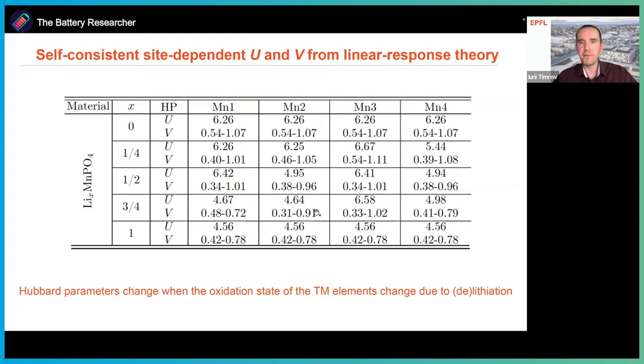So this is quite important to do consistently, because what is done in the literature nowadays is that people use empirical Hubbard parameters, for example, by fitting to the experimental oxidation enthalpies, and they use a unique global value across all concentrations of lithium. That's quite a drastic approximation. Nonetheless, it gives quite good results. Not sure if always, but in some cases it does. But what we do here, we really take into account more accurately what happens at the electronic level. We really computed it site dependent. So how each manganese changes its electronic state, its oxidation state, so the Hubbard parameter changes.